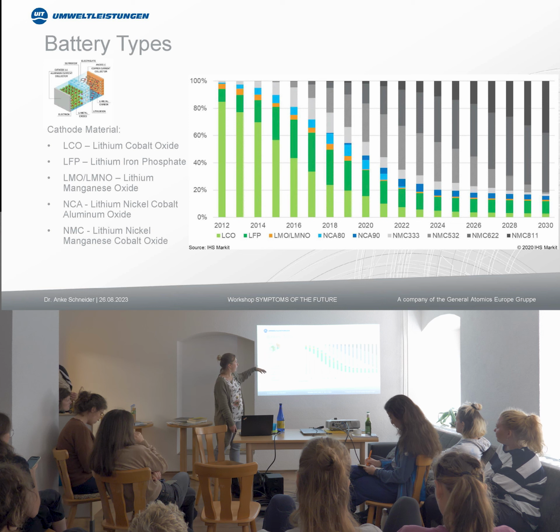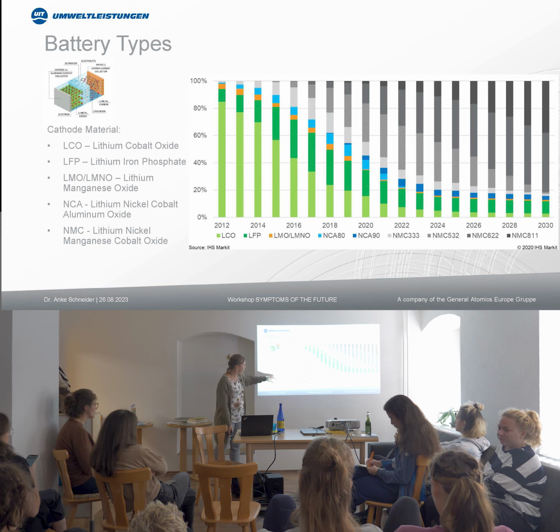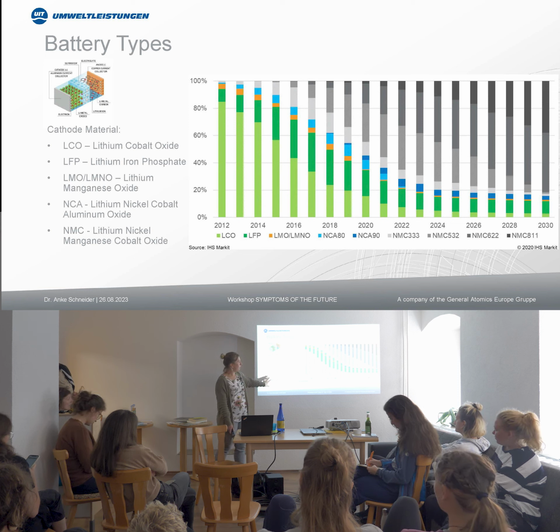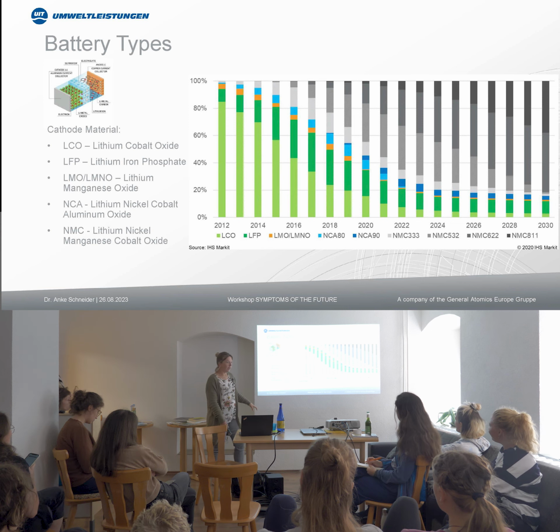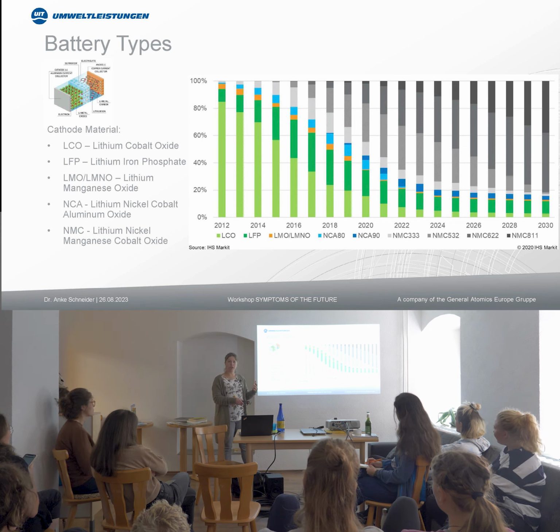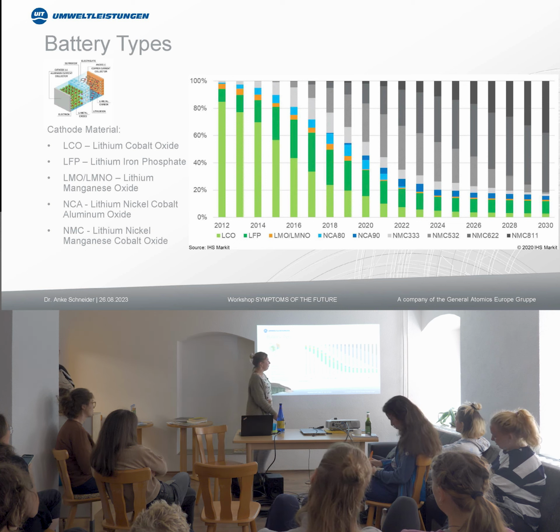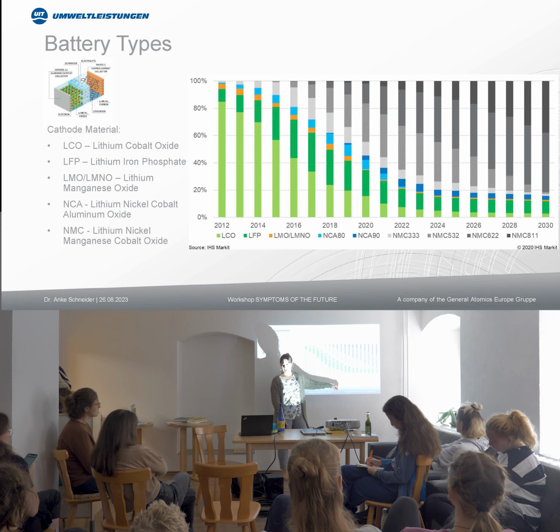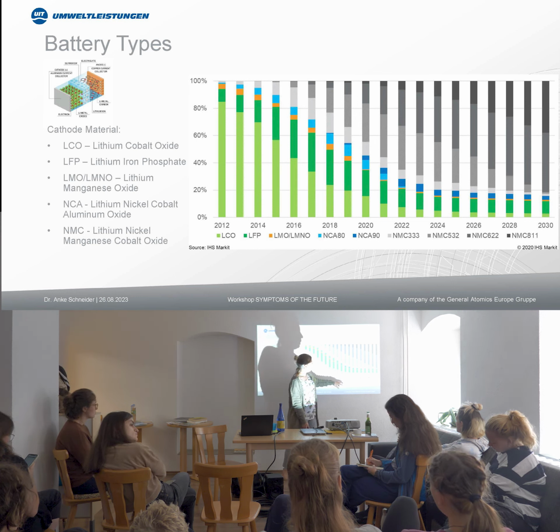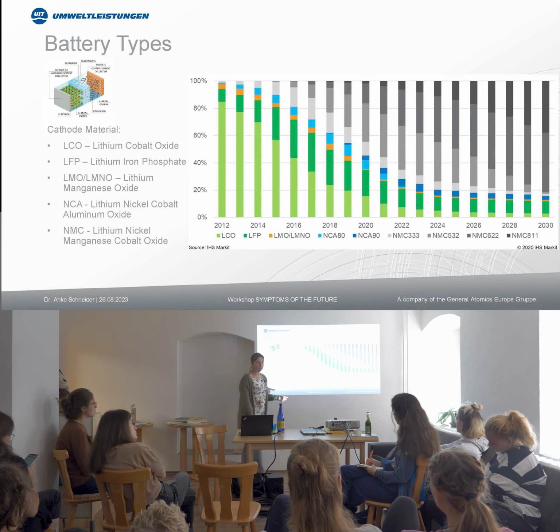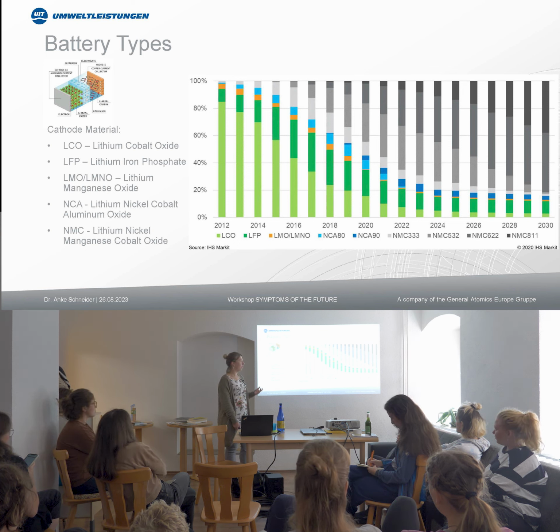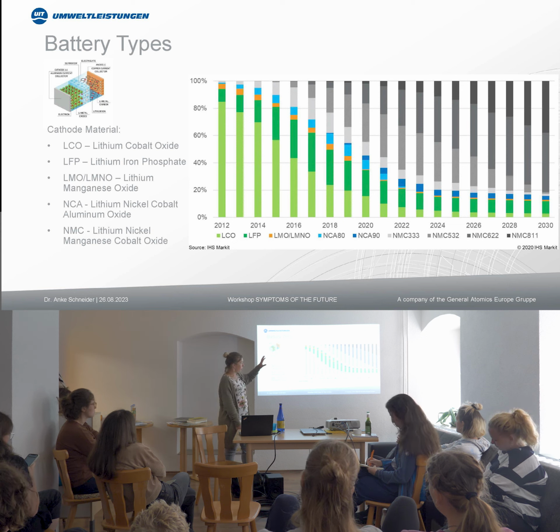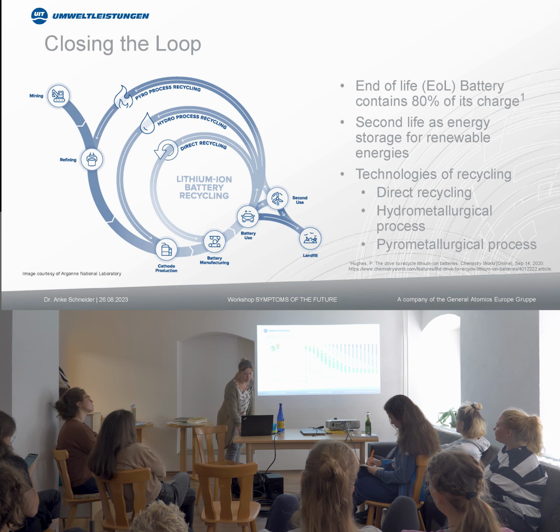The next step to get rid of the cobalt, or at least a little bit, they had lithium manganese oxide, lithium nickel cobalt aluminum oxide, and which is the main dominant battery type nowadays is this lithium nickel manganese cobalt oxide. And you see it's getting more and more complex because you want to optimize your battery technology. And if you have a look at this, there are 4 different types of this kind of mixture of oxides, and the industry tries on the one hand to optimize their batteries and on the other hand to get rid of cobalt and lithium because they are expensive and they have a very high supply risk. So that's basically the trends in the battery technology.